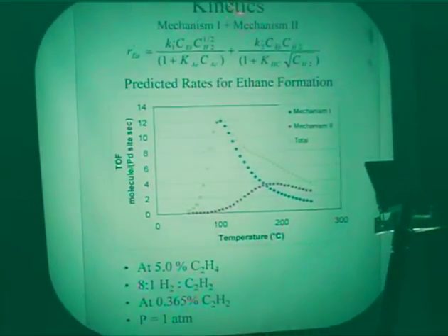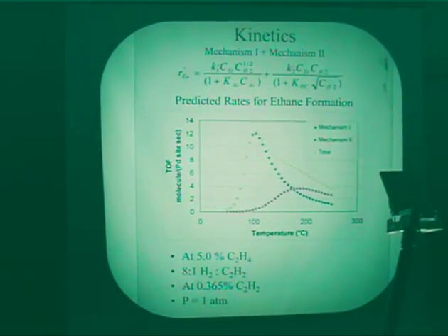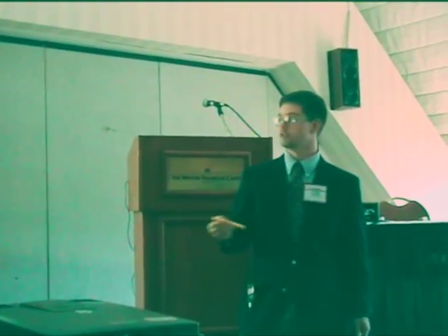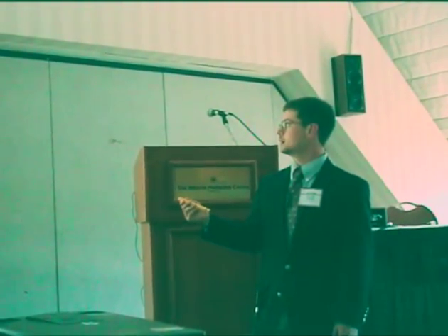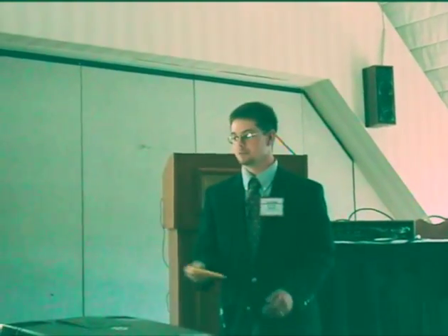Now, one unusual result is the half-order dependence in hydrogen. And as far as I can tell, or at least as far as I've explored, I can't seem to find this supported anywhere in the literature. So I guess we're proposing it. So it's interesting, but hopefully I can correlate it with something later.